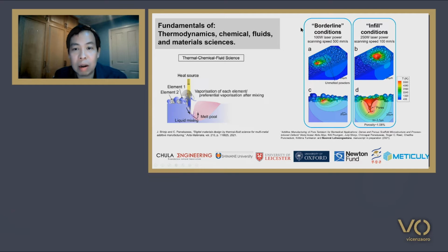This refers to the conditions that are barely melting the powder at the edge of the heat affected zone. For example, here is the work on our tantalum. We use only 100 watts laser power and a really fast scanning speed of 500 millimeters per second. You would see that there are some unmelted powder here.